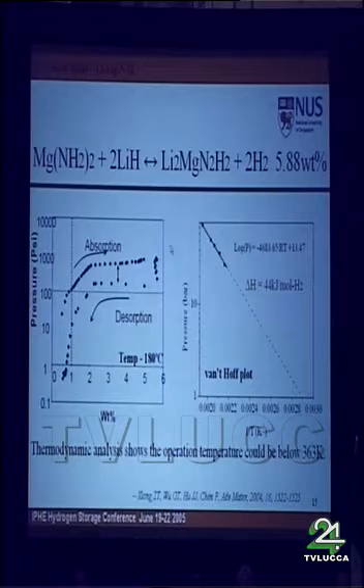It is absolutely different from the lithium nitrogen hydrogen system. And through a van't Hoff plot, we notice this system could operate at temperatures below 90 degrees Celsius. However, the kinetic barriers are pretty high. We have worked with Sandia people and found that the activation energy for hydrogen desorption is about 100 kilojoules per mole of hydrogen. So the next step should be on the materials engineering, either on the morphology of the sample or on the introduction of catalyst additives to the system.